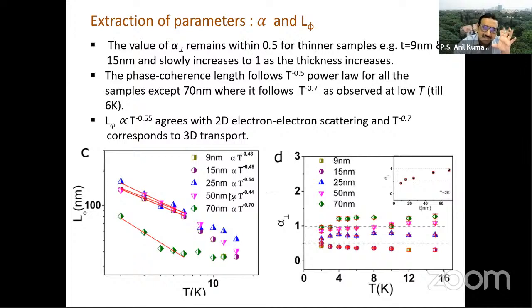Similarly, if you look at the temperature dependence of your phase coherence length, you see that for low thicknesses, it follows approximately 2D behavior with this alpha value coming close to 0.5. And as you go to higher thicknesses, it moves towards a 3D transport. So this is all happening because the system is also a little bit self-doped.